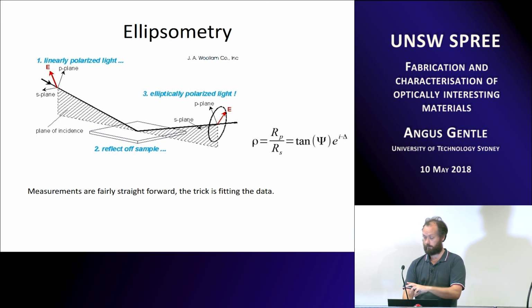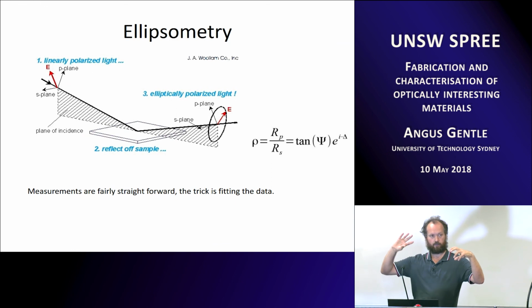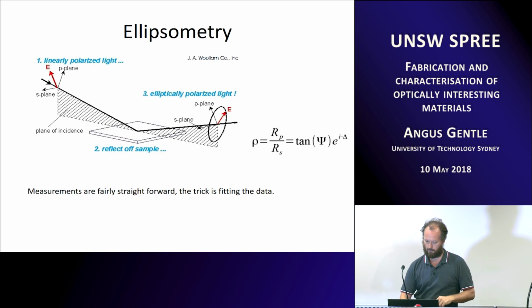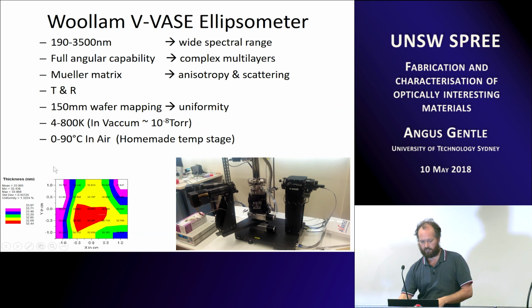A lot of you might know about ellipsometry. Basically, you have a polarized light source on one side, it bounces off the sample, then you look at the shape of the polarization on the other side with a polarizer that rotates around. Fairly easy measurement if you're doing straight samples. Adding temperature dependence, those sorts of things becomes more complicated. And also it's the fitting of the data that is the hard part. So yeah, we've got the sample mapping. So this was a spin-coated one. You can see it's thicker on the edges. So if you take a spin-coated or a sputtered sample, you can see the comparison of how thick they are.